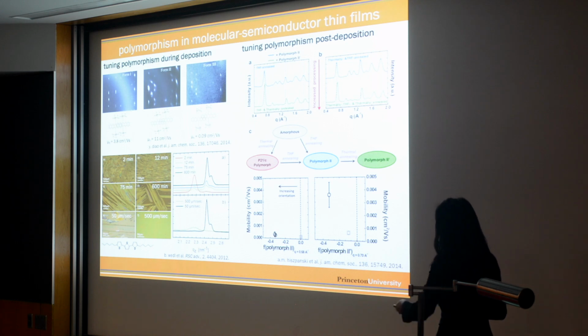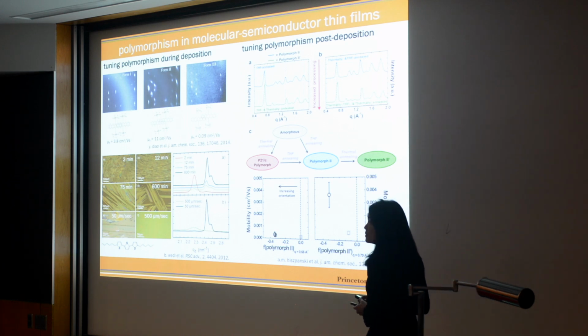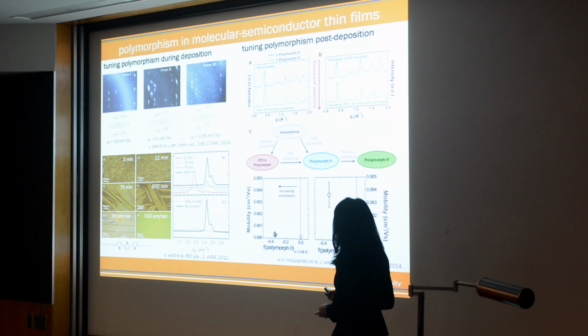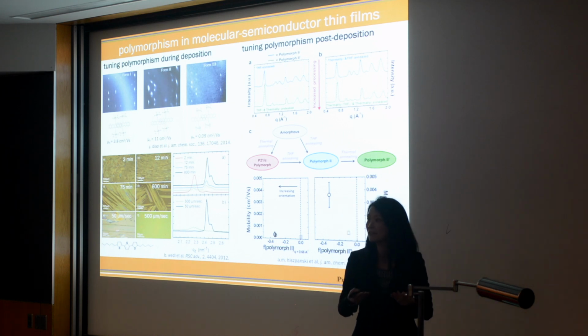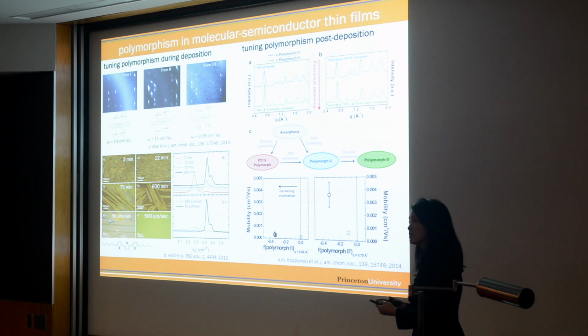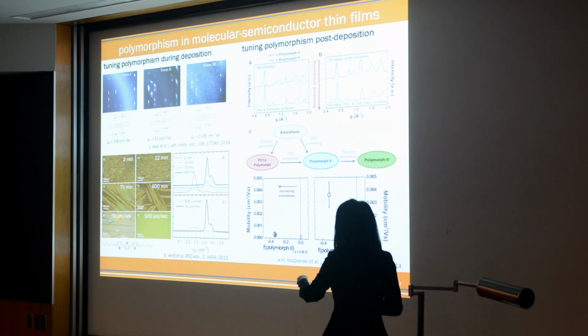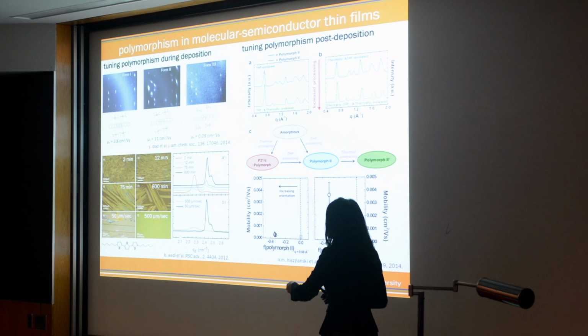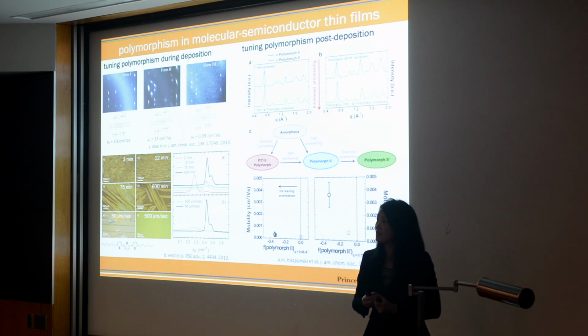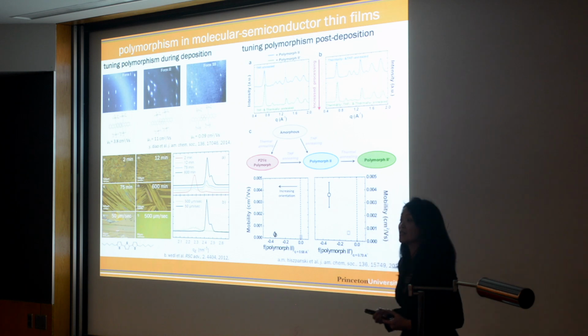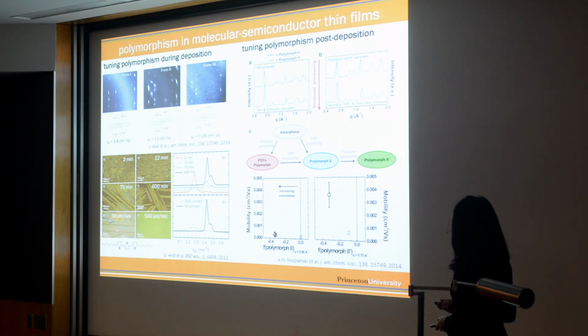Last but not least, this is a terthiazole oligomer from Yves Geerts's group in Belgium. And he's shown that depending on how fast the solvent evaporates, depending on how fast you spin coat the film, you can access a thin film polymorph. And you can see the crystal structure is different, the X-ray diffraction here. And this thin film polymorph, again, has differences in charge transport character.